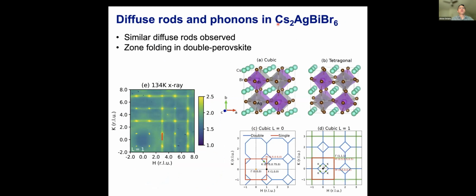So let me say a little bit more now on the double perovskite system that we're studying with diffuse scattering, IXS, and neutrons also. So this system has silver and bismuth ions on the B side. These are ordered in a rock salt arrangement as shown in these plots here. And you still have the tilt systems of the bromine octahedra here. And so you've got a tetragonal distortion that now occurs at a little bit lower temperature, around 120 K. So we see similar rods as we've seen in cesium lead bromide earlier, because there's effectively a folding associated to the larger unit cell, so a smaller Brillouin zone.